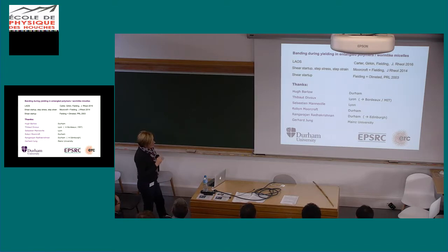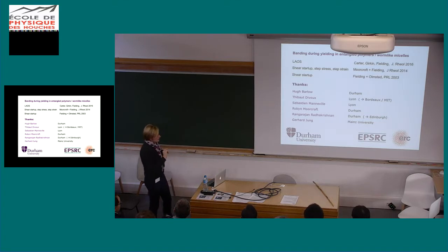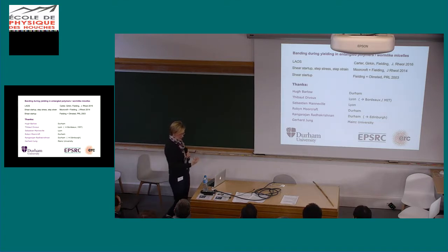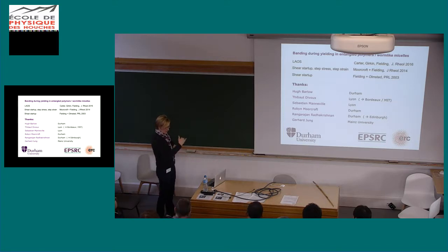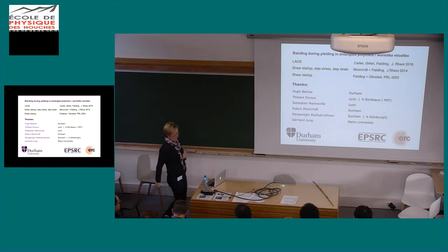Yes. Okay, so in truly continuum models like a fluidity model or in the tube models, it's true that we do put a diffusive term in. Actually, though, it turns out that the criteria for the formation of bands is very highly independent of that diffusive term. So you have a dispersion relation as a function of wave vector, and that's generally a plateau up until you get to wave vectors of order the inverse diffusion length scale. And so bands form on a macroscopic scale. You really just need the diffusion term to save you from having very tight interfaces on very short length scales.